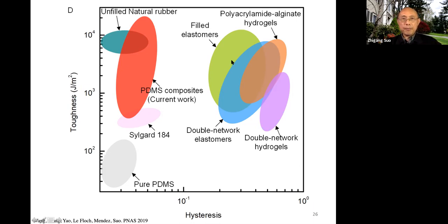However, it dissipates. Now, if you do unfilled, without carbon, and also test at a relatively small strain, then natural rubber actually has a very small hysteresis. Hysteresis is less than 10%. So for many years, people knew only very few materials, such as natural rubber, that can give you small hysteresis and high toughness. Now, with our design principle, we just make a PDMS with enormous toughness and very low hysteresis.